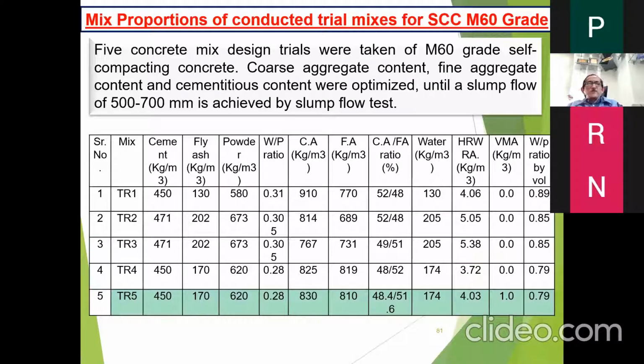And as I told you, we did 5 mix designs, and TR5, trial number 5, was finally adopted. The cement content was 450, because since this was an M60 grade concrete, 450 is the limit, as you all know, put up by the Indian standard 456, which puts a higher limit of 450 kg pure cement, and then you can add fly ash. So fly ash added was 170 kg, taking the total powder to 620 kg, with a water powder ratio of 0.28, 0.3.